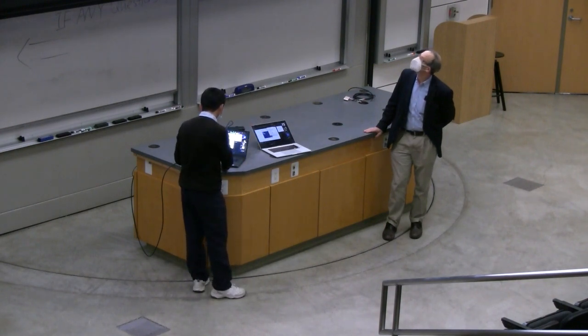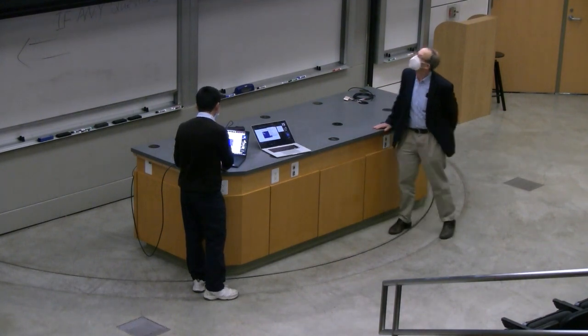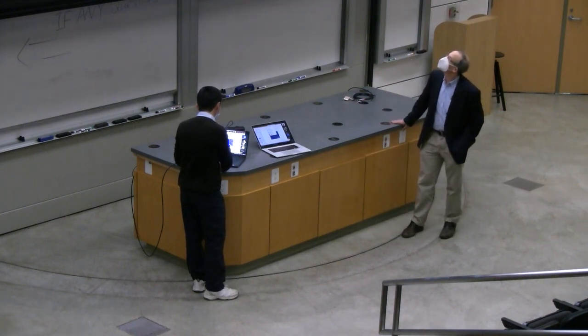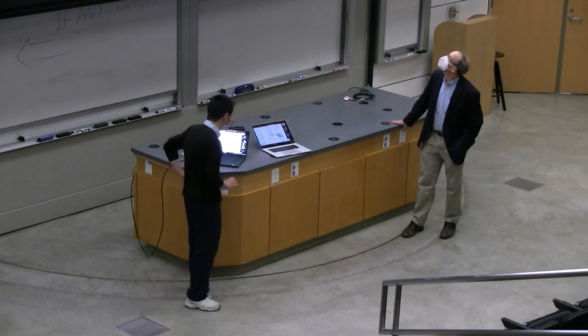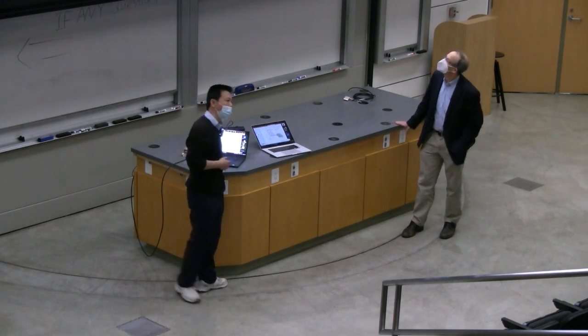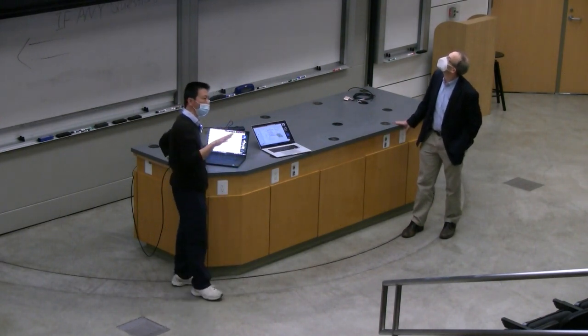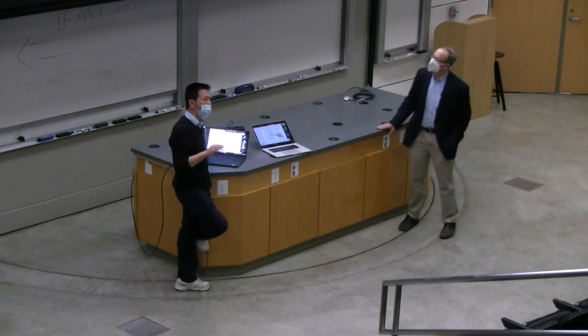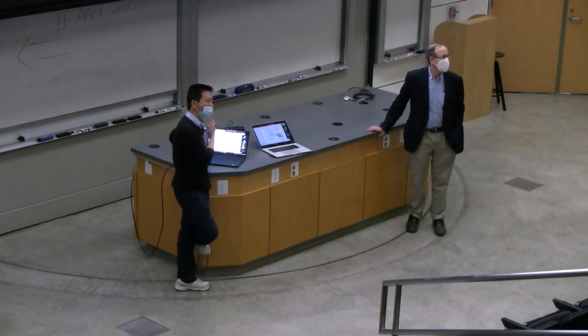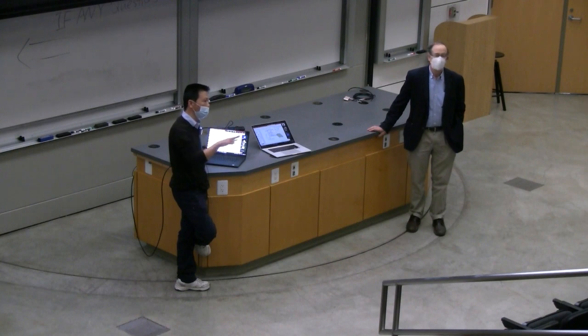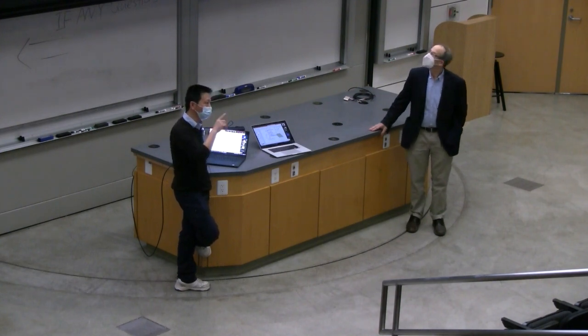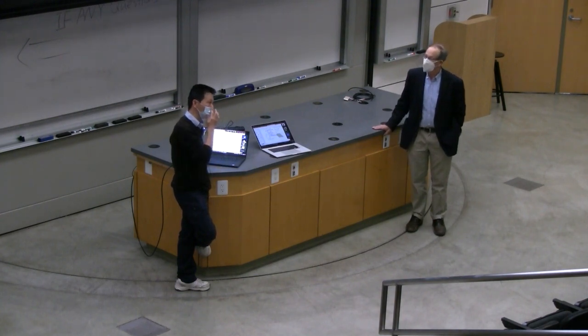Yeah, resistivity. So you can see in that case, the overall resistance is very high. So it seems in this case, at least in this sample, maybe the defect actually may dominate in some of the transport. So they never get a real metallic state. But what you can see is at least at the Mott insulator, the resistance shoots up dramatically. So there's a very dramatic change in the resistance.